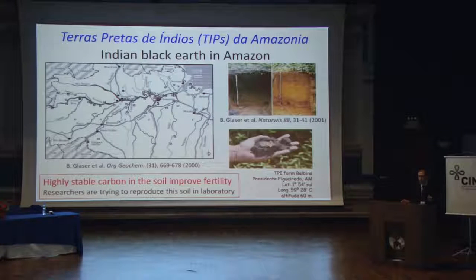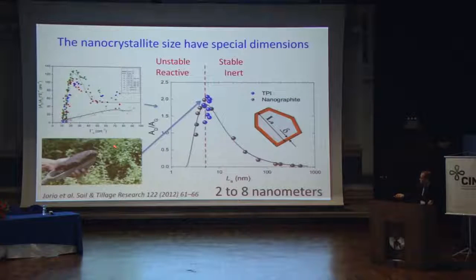If you remove the soil, it gets like a desert. And this is a very good soil for agriculture, and it's very stable. And it's related to rejects that they burned and put into the soil. So we did a Raman-based experiment fully based on this picture, and we learned what was the specific structure for these materials, and we are working now on taking leftover material from sludge, from many things, and trying to make a treatment to generate this kind of carbon that you find here and you could put back in the soil. Of course, also worried about contaminants and other things that you could find on this sludge and other trash.